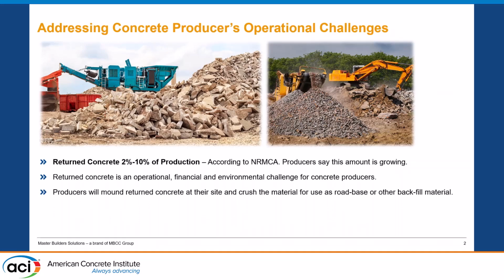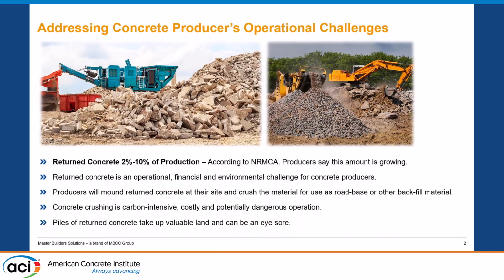So it's not uncommon to see producers mounting returned concrete at their site and either crushing it themselves or sending it off-site to be crushed at a later stage. This material then can be used either as a road base, backfill, or again as aggregates, as we just saw Professor Cavalim speaking. However, crushing concrete is pretty energy intensive. It is not very cheap, and dealing with chunks of concrete of various sizes and weights can be potentially dangerous. And again, depending on where the ready-mix sites are located, piles of returned concrete take up space, and that space comes at a premium. And it also can be an eyesore not only for the producer, but for the neighborhoods in which the ready-mix plants are inserted in.